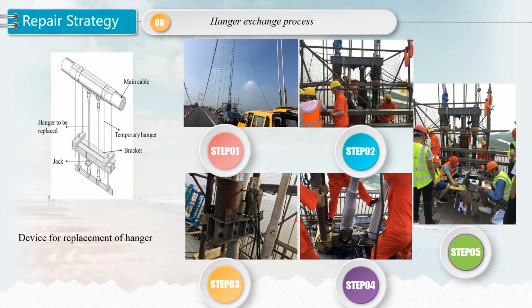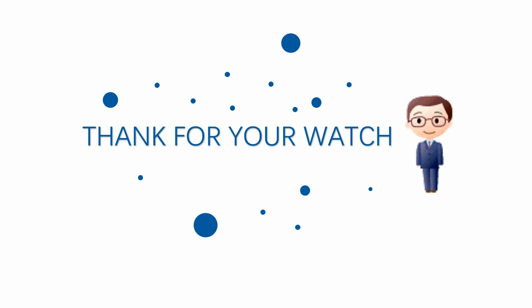According to the assessment from the fire department, the maximum temperature of the hangers was estimated to have reached 600 degrees centigrade because they are very close to the fire source. Therefore, the strength of the hangers is evaluated to be reduced by 40%. The hangers were judged to have suffered irreparable damage by fire and not fit to continue in service. Hence, the bridge authority decided to replace these hangers. A novel device was designed for replacement work. The picture taken from the site is shown in the right picture. That's all. Thank you.